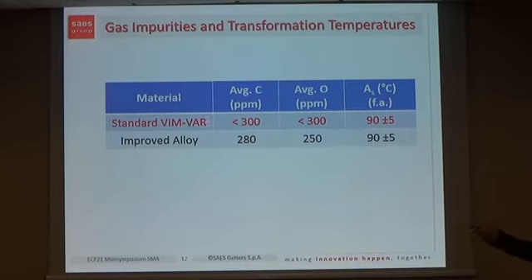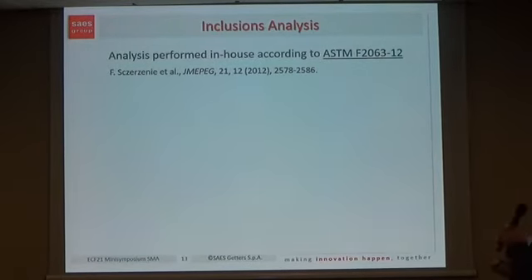This is our standard historical reference, standard materials and our improved alloys. As I mentioned at the beginning, looking at the carbon and oxygen doesn't help in having some indication about the potential inclusion size or area fraction and the effect on fatigue. And that's an important outcome from our R&D activities. Then we perform in-house inclusion analysis following the recommendation of ASTM F2063, that is the standard practice for nitinol used in biomedical devices.